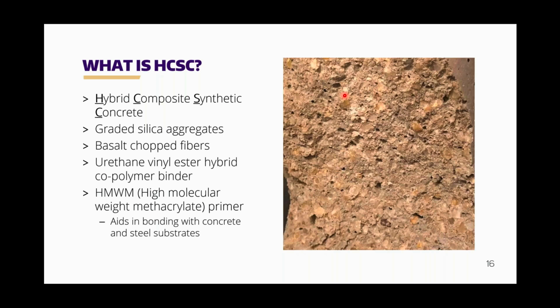To aid this material in bonding with concrete and steel substrates, a high molecular weight methacrylate primer is used. And this really helps to bond the two materials together and prevent the binder from leaking into the existing concrete, so that you get a good cross-linking between the binder and the aggregate.